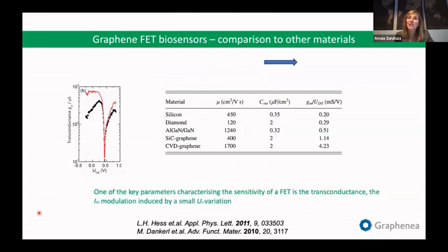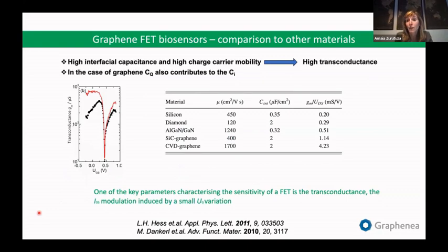Okay, so if we compare graphene to other materials on these two parameters I just mentioned, mobility and interfacial capacitance, I got this from these two papers, and these are already quite old, so the mobility values of graphene have improved quite a lot. But even here, if we take CVD graphene, you can see that the value is much better than the other materials. And the interfacial capacitance is also much higher than silicon. This translates in these transistors to a high transconductance, and this is what you need to have a high sensitivity, basically. For more information, you can check those two papers.